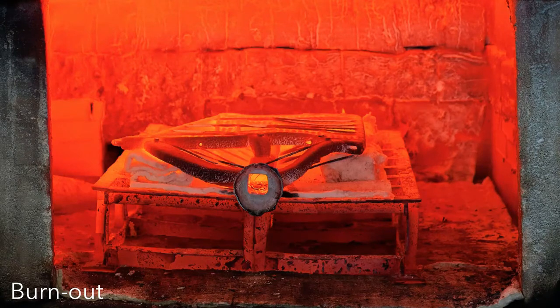PLA is basically polymerized cornstarch, burns out very cleanly. Likewise, the PMMA powder that voxeljet uses, in addition to burning out cleanly, has an interesting effect. It has a negative coefficient of thermal expansion, so it doesn't stress the shell, it doesn't expand as it heats. So it's one of the preferred pattern printing techniques within the foundry industry.